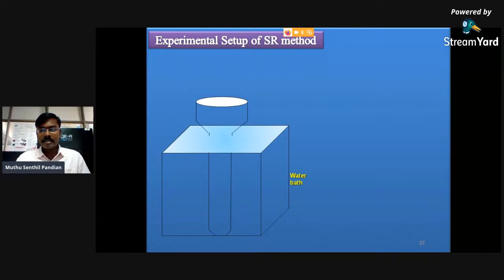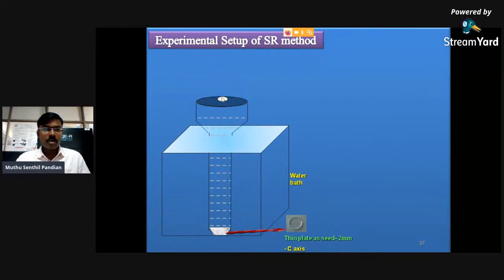So the experimental setup of this SR method consists of the glass sample, and this glass sample is kept inside the water bath, and a thin plate like a seed crystal is mounted at the bottom of the glass sample, and a small hole is made on the glass sample for solvent evaporation. After that, we pour the saturated solution inside the glass sample, and after a few hours, due to gravity driven concentration, all the solute molecules approach the seed crystal surface directly.